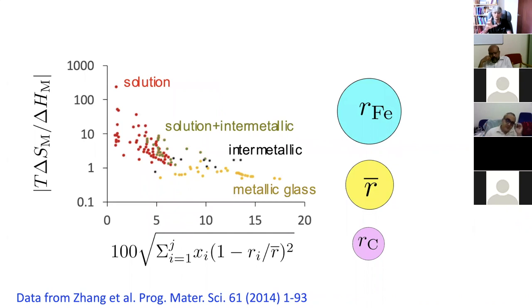So we are looking now into design rules for high entropy alloys. And these have their origins in the Hume-Rothery rules and so forth, where if the atomic misfit is large, then you tend to get precipitation rather than a solid solution. So the way that the atomic radius is calculated is, say you have a particular radius for a particular atom and another radius for another atom in your solution. You take the average of those two, and R bar is the mean radius here, and this is for a particular element in your solution, and you scale that by the concentration of that element. So this is a measure of the misfit in the solid solution.